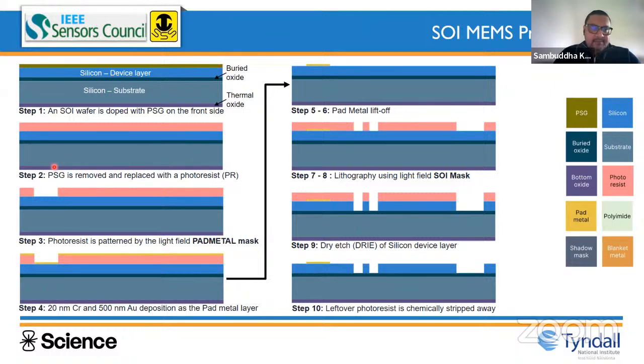And then in the second step, we remove the PSG, which is phosphosilicate glass, and then we replace it with a photoresist. After we do a photoresist spin coating here, we perform photolithography of the pad metal mask. This is the first mask. We do a lift-off process, where there is a metal layer of gold and chromium. Gold is 0.5 micron and 20 nanometer of chromium, deposited using the e-beam evaporation technique, and that creates the pad metal first.